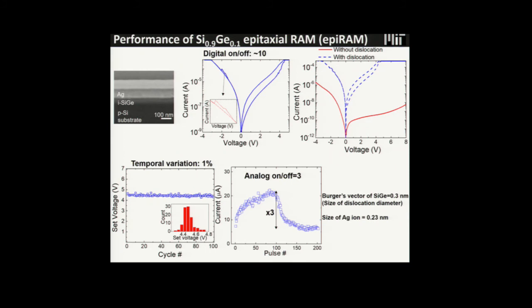What's the consequence? As mentioned, we use a single crystalline material, so it has super uniformity. It's super uniform. When you cycle 100 times, there's no variation in set voltage. So it worked ideally. Your cation was completely caged into the dislocation, so it is extremely uniform. All right?